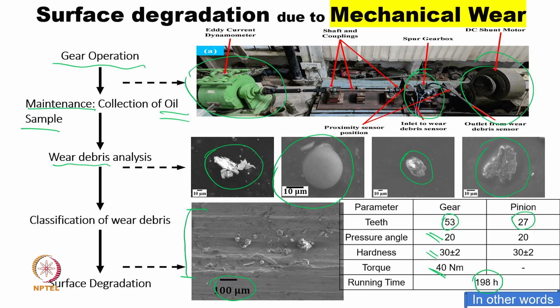We are able to see the debris, we are able to magnify the surface and see that yes, there are a number of particles on that. So, that is why I say wear analysis through oil, and then we can do a classification also. We can say there is a cutting wear, a very long fiber, and then long wear, then the particle has a dimension in one direction, and a smaller dimension in the other, maybe D1 here, and this is D2. And if this ratio D2 by D1 is very large, then we can say this is a kind of cutting wear. And then the plate form indicates sliding wear, and when we have a spherical particle, mostly fatigue or some sort of rolling motion is happening. So, we can really judge whether the surface is degrading or not.